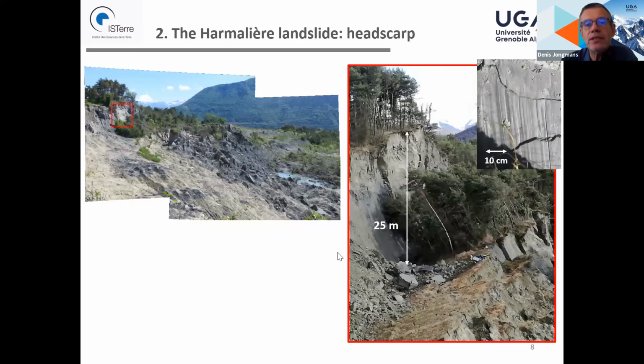If we look into more detail, here is the main scarp. At that site, it is 25 meters high, and you see this very stiff clay, which is really a soft rock at this state. You saw the motion, with a rotation of the block of clays sliding along a slip surface. And just after the landslide, it was possible to observe some linear striae showing that the motion was really a rigid motion with friction.